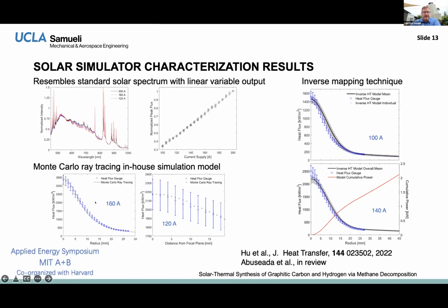When you see 160 amps or 120 amps here, that's the actual current going into our bulb. We calibrated all of that so we could find the heat flux distribution as a function of radius. Again, this is a symmetric problem, and you can see that our radiometer and heat flux gauge results fall largely on top of each other. There are a few nuances because there are some changes in the experiment that we had to make, in particular because the heat flux gauge is outside of the reactor, so it's characterized outside of the quartz window, and we had to make adjustments for that. But otherwise, we're pretty happy with the calibration.